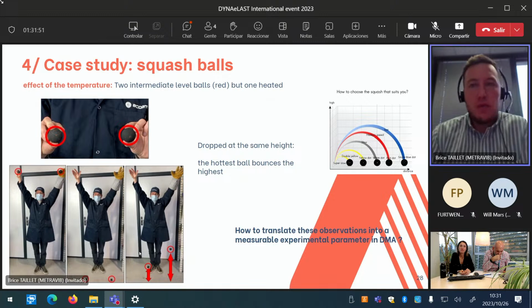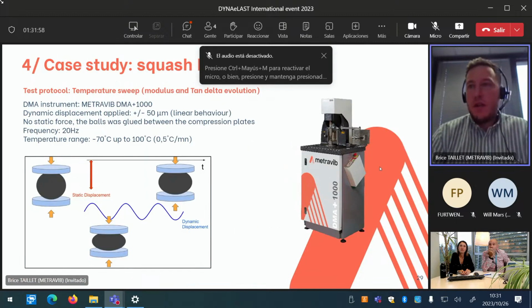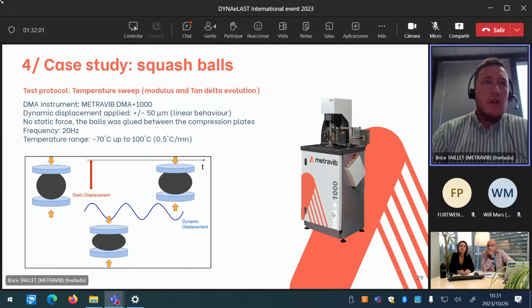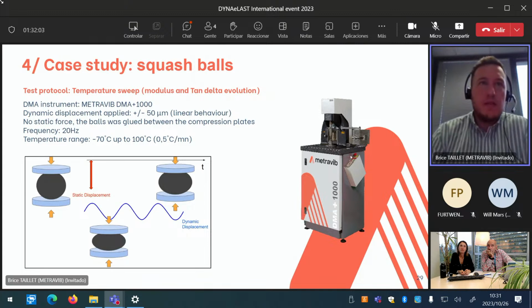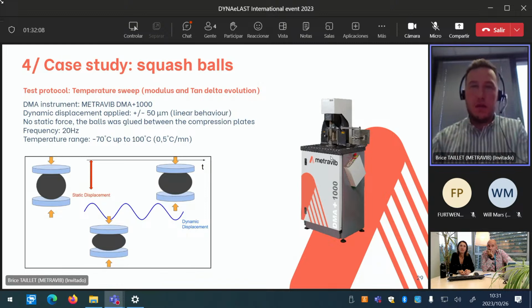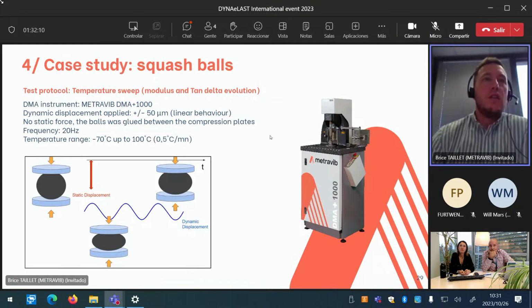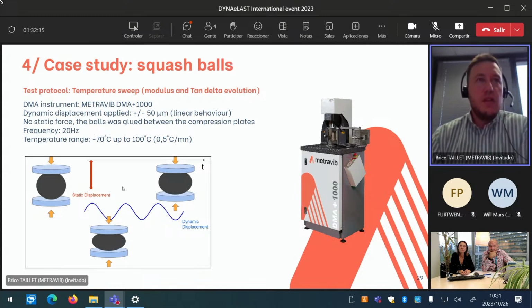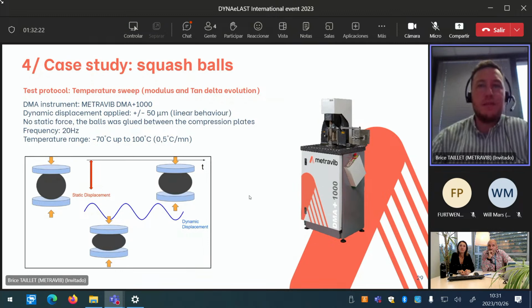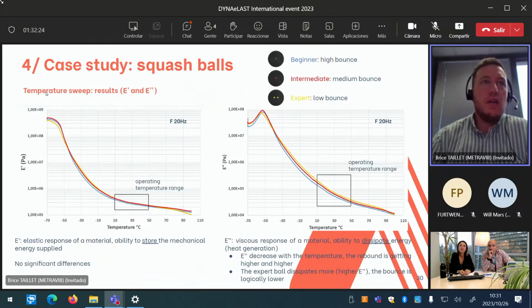So once again, how to translate this observation into measurable experimental parameters in DMA? For this, we use a DMA+1000. We apply a dynamic displacement of plus or minus 50 micrometers. That is to say, in the linear behavior of your materials. No static force. The balls were glued between compression plates. We use a frequency of 20 Hertz, and the temperature range was minus 70 degrees up to 100 degrees. We apply a temperature sweep.